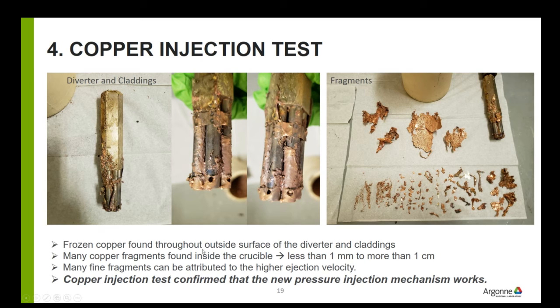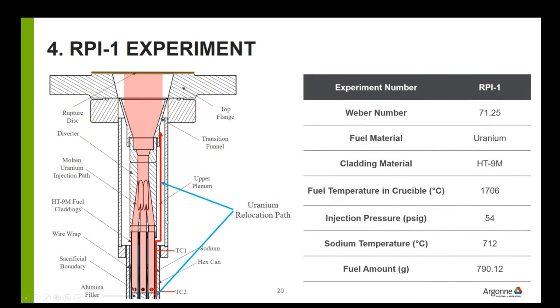So from this copper injection test, we confirmed that this new pressure injection mechanism works for our main experiment, and we moved on to our main experiment. Again, this figure is our test section design, which consists of 7 cladding pins. And this table summarizes our RPI1 experimental conditions. The fuel material is uranium metal, and the cladding material is HT9M steel. The fuel temperature inside the crucible was 1706 degrees C, and the injection pressure was 54 psig. The sodium temperature inside the test section when uranium was injected was 712 degrees C, and the fuel amount used in the RPI1 experiment was 790 grams.